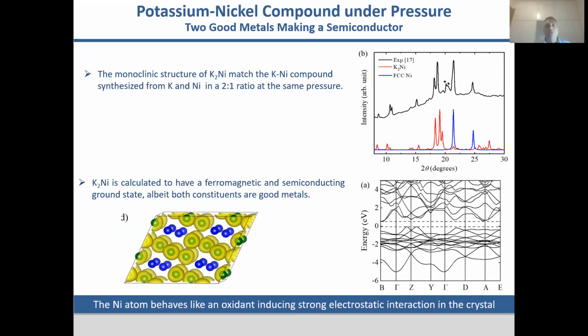Up here, things look trivial. However, what is, at least for me, very interesting is that if we calculate the band gap of this compound, it looks like we have something like a 0.6 eV gap. This means that this compound in reality is a semiconductor or an insulator. So you combine two good metals like potassium and nickel, and you end up with something that is insulating. Now we have the full story about why we can form compounds between potassium and nickel, due to the change of character of potassium and so on.